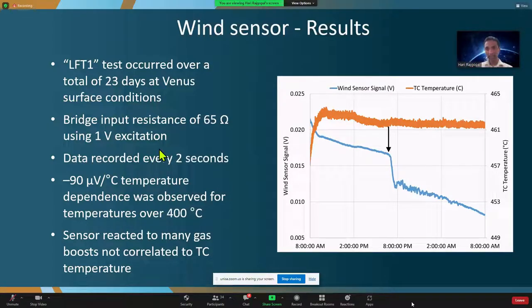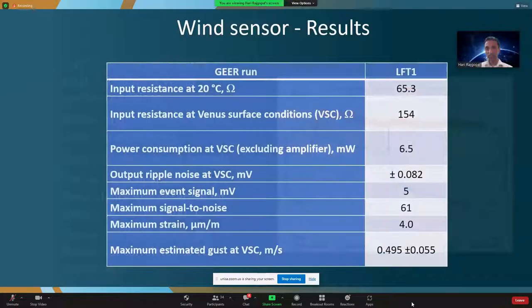If we go to the next slide, I can show you the actual results. The input resistance at 20C is about 65 ohms. The input resistance at Venus surface condition is about 154. The power consumption of the sensor itself, excluding the amplifier, is about 6.5 milliwatts. Maximum strain is about 4 microns per meter. And then the estimated wind gust at Venus surface condition is about 0.5 meters a second. We were targeting between, say, 0.25 and 2.5 meters a second. So the initial results are very promising.